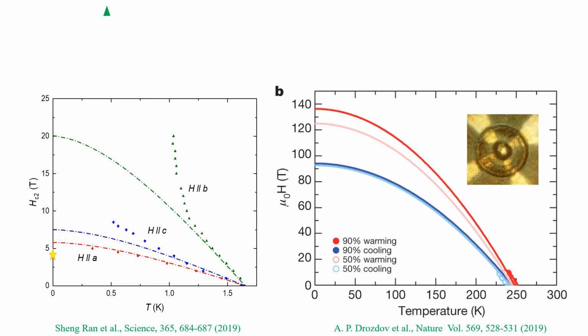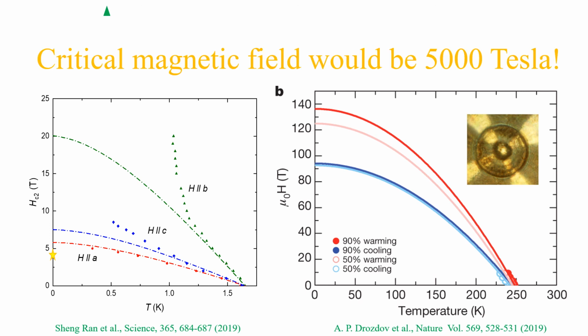To give you a comparison, last year, scientists found room temperature superconductivity in pressurized lanthanum hydride. There, the critical temperature is 250 K, and the critical field is about 100 Tesla. Now, if we scale the critical temperature of uranium ditelluride to the critical temperature of pressurized lanthanum hydride, the critical field of uranium ditelluride would be 5,000 Tesla. This is extremely high.